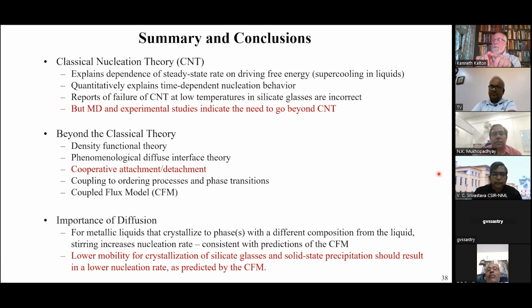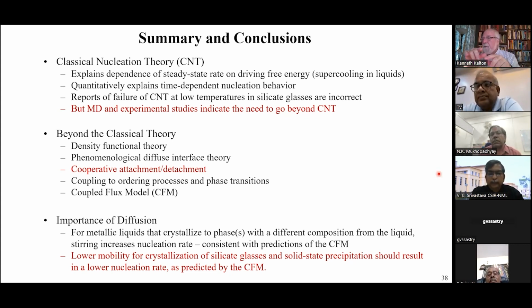But what happened in this case was we supercooled the liquid to the point where it was in the equilibrium phase field of the C14 Laves phase. That's what should have formed in equilibrium. But we hadn't cooled it deeply enough that we had entered the region of quasicrystal stability. We were still in the C14 stability range. And instead of nucleating the C14, it nucleated the quasicrystal. So that's why it was metastable. We weren't in the right temperature range for it to be in the stable phase.